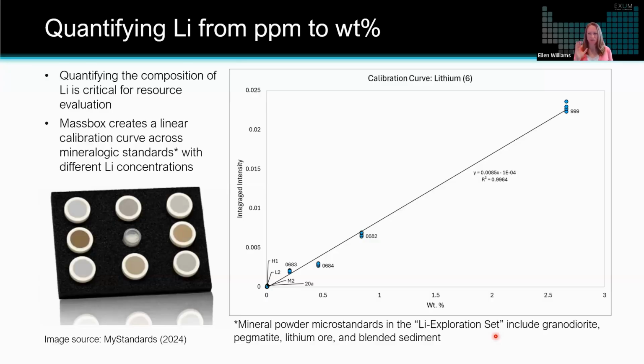So we have these reference materials that we can analyze in the same analytical session. And then we have the measured intensity of the lithium signal with our technique. And we plot that against the known concentration on the x-axis here. And this is how we create a calibration curve. So we see that across these different lithium standards, we've got everything from 12 parts per million in one sample, all the way up to 2.6 weight percent in another reference material.